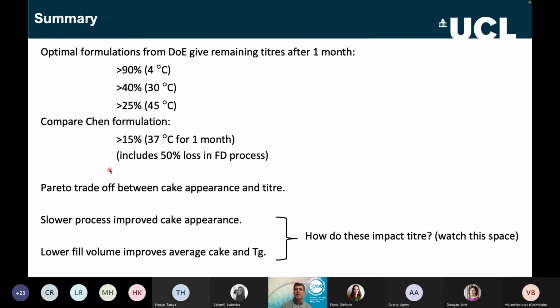Okay, so that is where we are, and I think I can pull all that together in terms of how it's performed. Excluding the 50-day data I've just shown you, this is the performance of the optimal formulation from DOE after a month at different temperatures, and we can see we get 90% remaining titer at 4 degrees, and 25% at 45 degrees, which is actually pretty good.